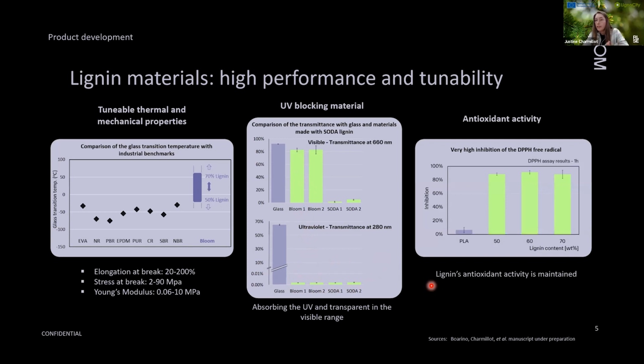We also know that lignin is usually an antioxidant, so we measured if this activity was maintained after the crosslinking, and indeed all the elastomers that we measured still exhibited a high antioxidant activity. So this was measured by this DPPH assay. DPPH is a free radical, and here we are basically measuring the inhibition of this radical. And you can see that all of the elastomers made with different lignin content show really high activity. And those kinds of properties were obtained without adding anything to the materials. So you can think that, combined with what you have previously presented, we can have a really interesting material.